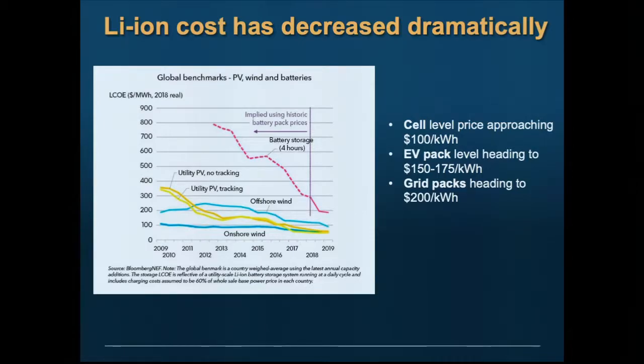And this is mainly a cost issue, right? That, you know, lithium-ion, if you extrapolate this, I started in the field well before this when lithium-ion was well over $1,000 per kilowatt hour. Today, at the pack level, so this is fully packaged with electronics, it's below $200 already. And at the cell level, if you just want to buy cells in large volume, it's hitting about $100 a kilowatt hour. And that's coming down from over $1,000 a kilowatt hour.